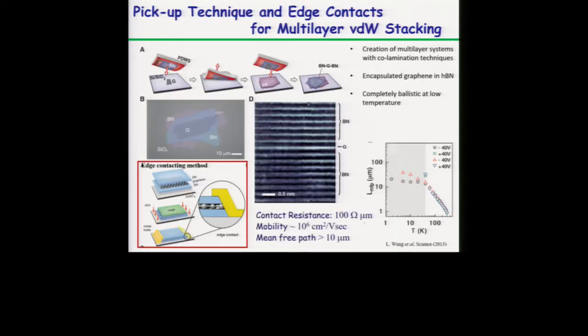The first heterostructure that was made out of this, I will call it a type 1. Actually, it's boron nitride with graphene. It was made in Philip Kim's group in collaboration with James Hone at Columbia and Kenji Watanabe, right? They were using boron nitride to pick up graphene, and at the end making these boron nitride, graphene, boron nitride heterostructures, and you can see they are atomically smooth. Since you're using tape to exfoliate each of these layers, you could think it might be full of dirt in between, but they are actually atomically flat.